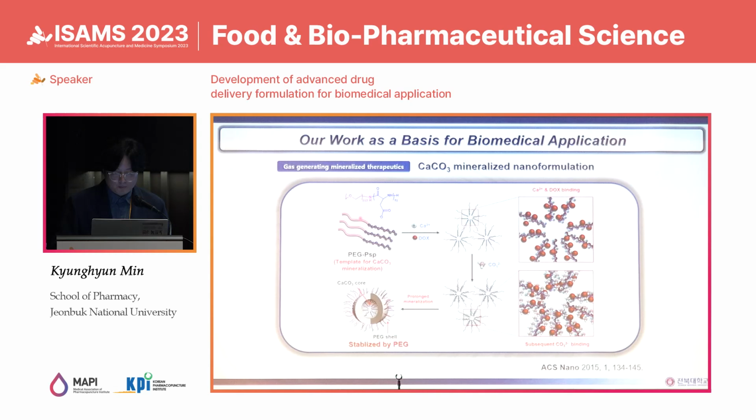Anionic polyaspartate serves as a nucleating template for calcium carbonate mineralization. The consequential binding of calcium ions and carbonate ions induced supersaturation and thus resulted in the formation of mineralized nanoparticles. The addition of drugs is also optional.